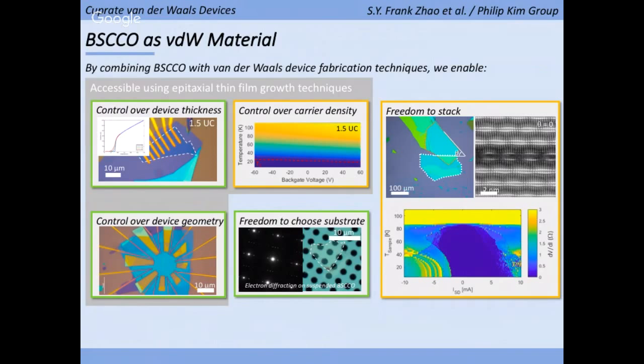Classically, people have tried such an experiment using bulk crystals, usually, or whiskers. And usually there, you have to anneal the crystal to get a good interface. So it's a little bit different in that sense. We don't do any annealing. We just put one on top of the other. And we already recover a very good interface. So basically, we're still working on it.